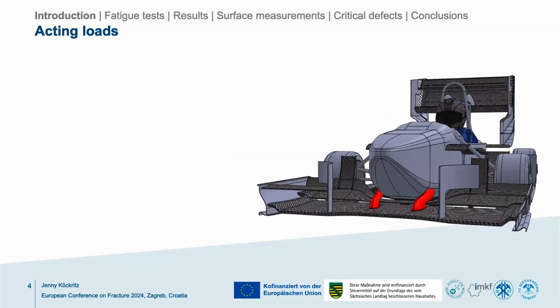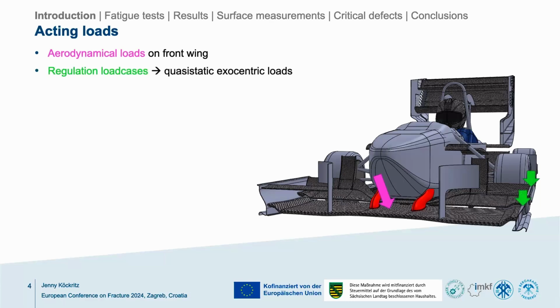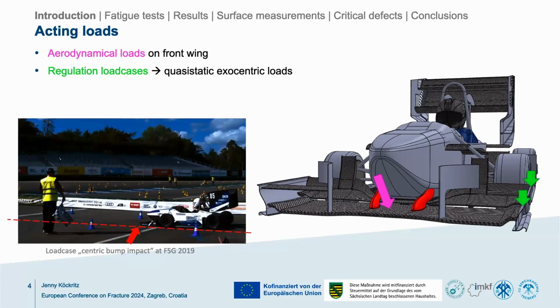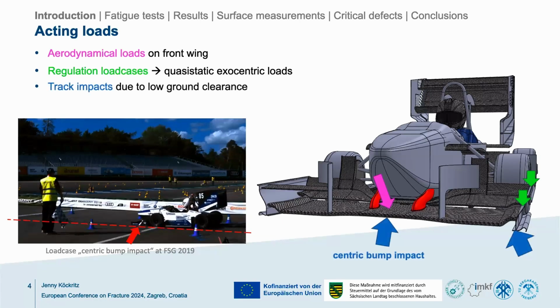So the loads that are acting are, as I mentioned, 1, the aerodynamical loads, 2, some quasi-static loads, which come from regulation, not that important. And 3, as I showed in the video, due to the low ground clearance of these front wings, you very frequently have impacts with the road if we have bumps. It's highlighted by the red arrow there. It's actually an impact. And these impacts can happen either on the edge or in the center of the front wing. And we focus on the centric bump impact as a fatigue load because it is the maximum load that occurs. That's also validated by measurements. And it occurs so often that we have to consider fatigue here.